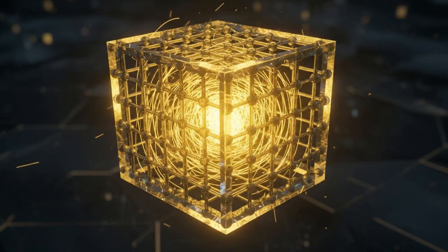That is an absolute eternity in the quantum realm, making them profoundly useful not just for solar panels, but for advanced photocatalysis and chemical manufacturing. By engineering complex heterostructures that combine the massive light-absorbing capabilities of three-dimensional perovskites with the transport properties of monolayer semiconductors, scientists have created systems where interfacial hole transfer occurs in a mind-boggling 100 femtoseconds, while electrons transfer in roughly 3 picoseconds. Because the hole rapidly diffuses away from the interface within the thick perovskite layer, the physical distance between the charges increases dramatically. This coupled long-range diffusion and ultra-fast interfacial transfer results in near-perfect efficiency.